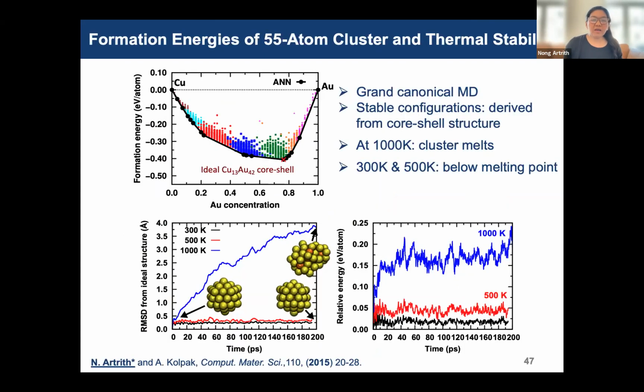And not only that, we can also combine Monte Carlo and MD simulations to make sure that the structure we found is really stable in different conditions. You can see that at 300 Kelvin and also 500 Kelvin, the structures still stay core-shell, with gold in the shell and copper in the core. And there are also many different compositions, as you can see here, like the convex hull or the phase diagram. So we can really sample many different compositions with the help of machine learning models. And at 1000 Kelvin, you can see that the copper gold nanoparticle starts to melt,